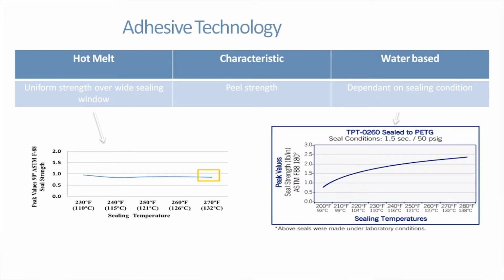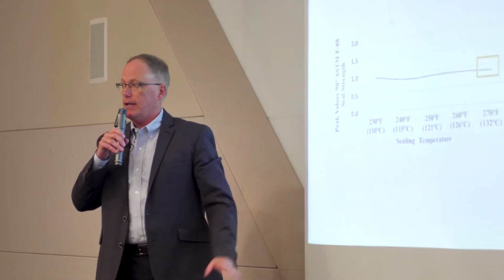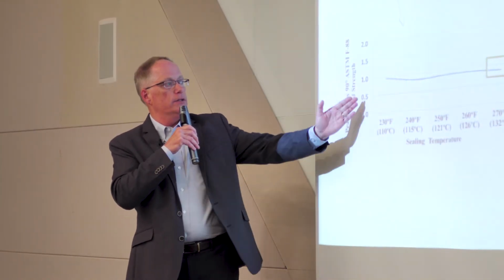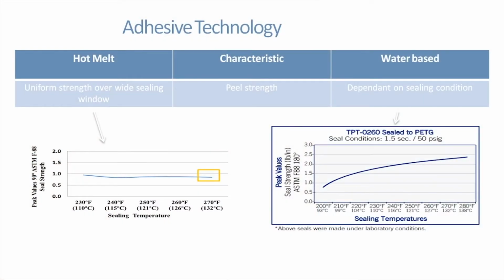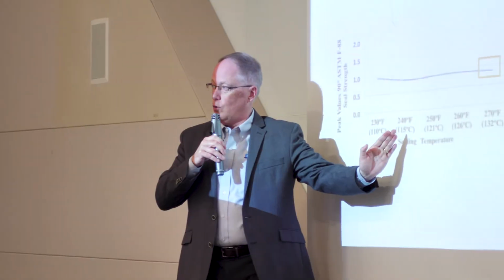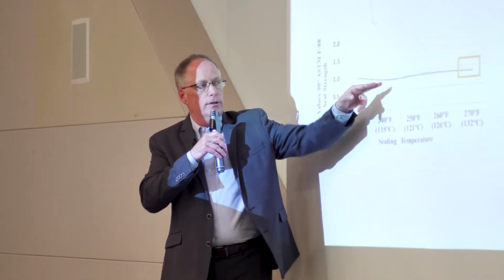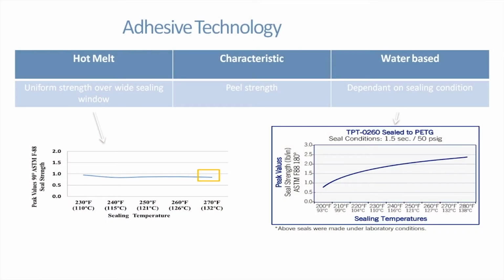Peel strength is the next characteristic we're going to talk about. We have two seal curves here, outputs from our customers' sealing processes. This is your sealing temperature on the x-axis, and the output is the seal strength in pounds per inch. One slight difference between the two technologies: with hot melt, you're generally going to have a flatter seal curve, meaning at your low temperatures versus your high temperatures, your peel strength should be somewhat stable. From a statistical standpoint, there can be some benefits there. With water-based, you generally have an upward trend in the seal curve.